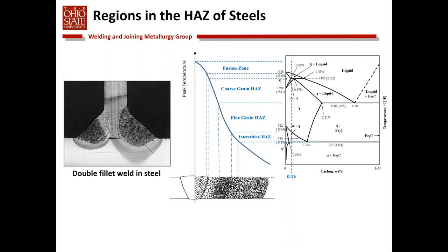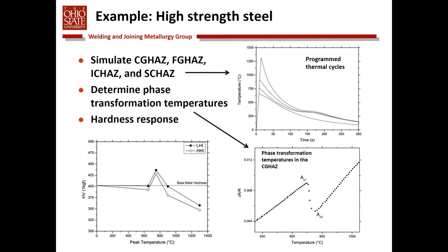So here's an example of heat affected zones that would form in welds, and a schematic that probably most of you have seen in terms of the different regions that form in the heat affected zone of steels. And again, we can use the Gleeble to basically simulate any of those given regions in a small sample. Here's an example of some work we've done with some high strength Navy steels, where we can program in the Gleeble different thermal cycles.